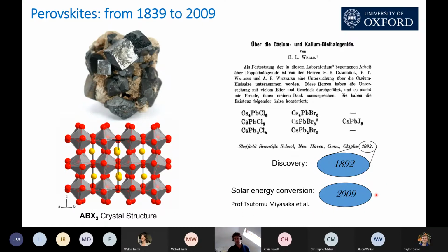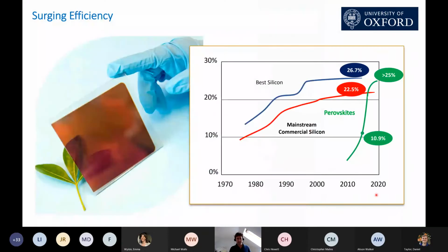where they used them as small quantum dots to absorb sunlight in what were then dye-sensitized solar cells. So we started working on these materials in about 2010 and very rapidly found that we could process thin films of these perovskites. This is just an example of an evaporated perovskite layer on glass, and that just as a thin film absorber material, they could be extremely efficient. And we reported over 10% efficiency in 2012. And since then, the whole community's really pushed the technology and the efficiency of these devices up to beyond 25%, and they're not at their ceiling yet.